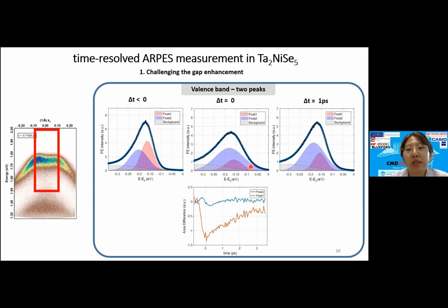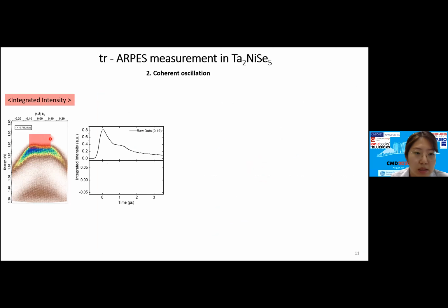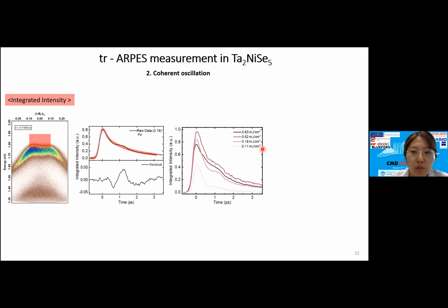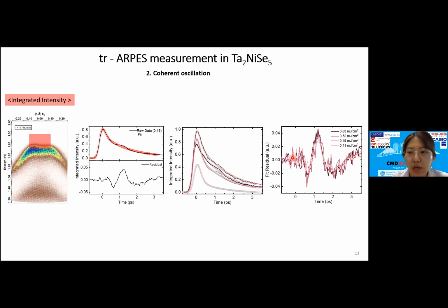Now we are going to see the dynamics of this missing spectral weight. So we integrated only the top of the band. This integrated intensity shows, on top of the incoherent excitation and then relaxation, a small oscillatory behavior, and we cleaned it out with fitting, and then we can see clean oscillations. For different pump fluences, all the measurements show this oscillatory behavior, and we can see this clean oscillatory behavior over many fluences of optical pumping.